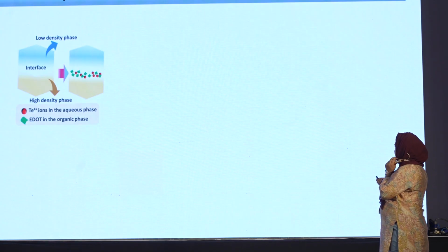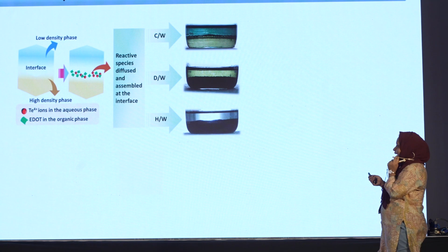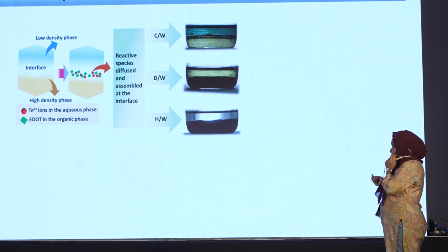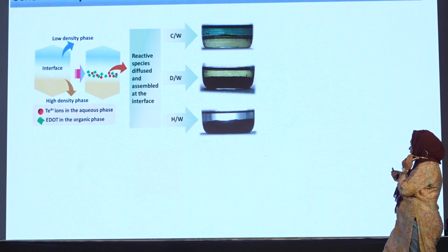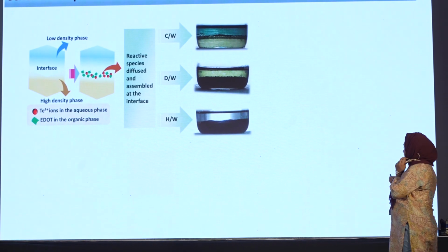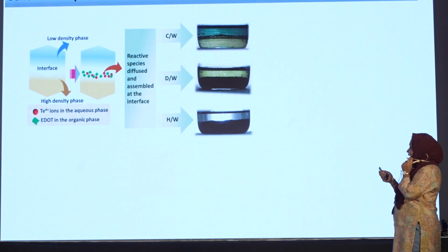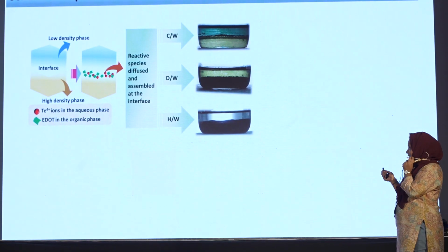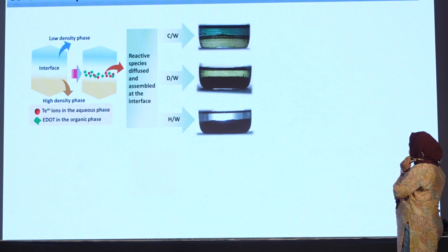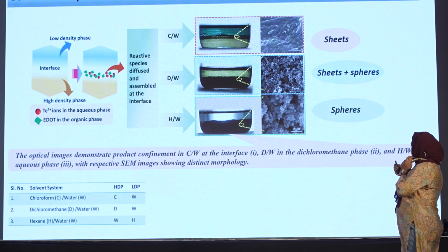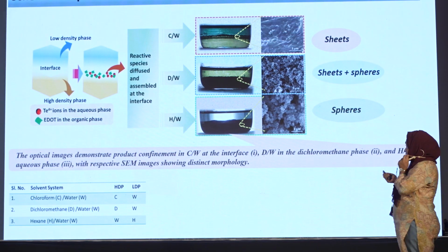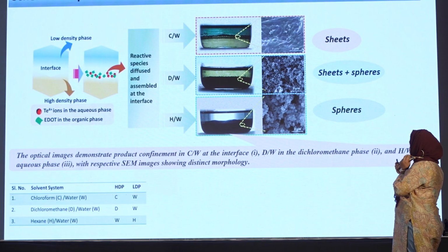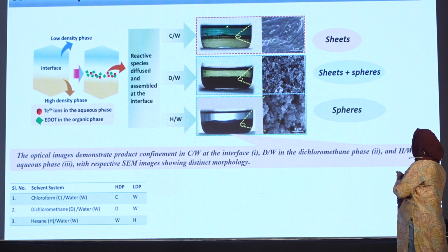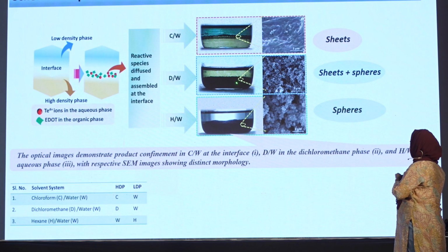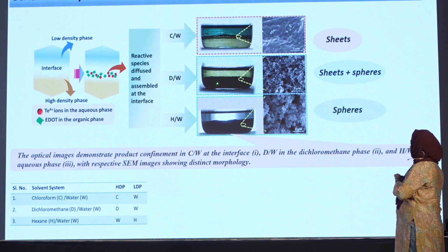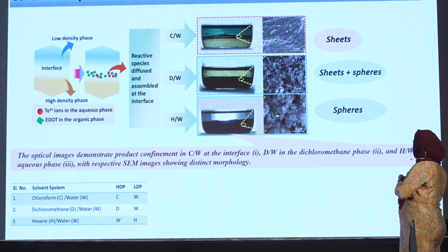This is the schematic representation for the synthesis. We have employed immiscible systems of three solvent systems: chloroform-water, dichloromethane-water, and hexane-water. In this, tellurium 4+ ions are taken in the aqueous phase and E-DOT in the organic phase. After the reaction, we have seen product confinement at distinct phases. For the chloroform-water system, it is in the interface. For the dichloromethane-water system, it is in the bulk organic phase, and for hexane-water, it is in the bulk aqueous phase.